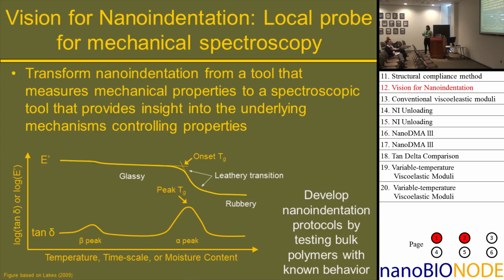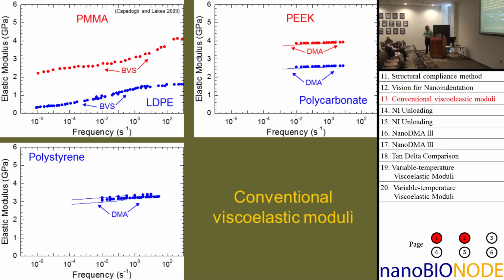One is this onset glass transition, which would be important for engineering materials. If you have a material and you want it to maintain its mechanical properties, you don't want to go beyond a condition where you start to go off this peak. But in terms of the molecular scale dynamics inside of a system, often the peak of the glass transition is more interesting. So I'm going to develop nanoindentation protocols by testing bulk polymers with known behavior that you can do conventional measurements on.